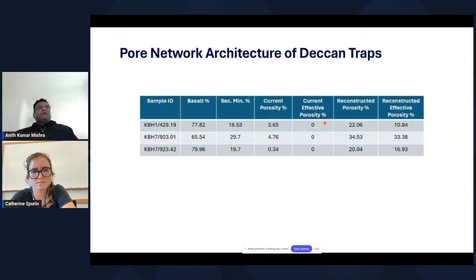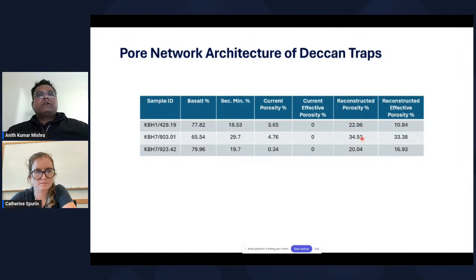So this is a table showing the basalt, the secondary mineral percentage, the current porosity, and the current effective porosity for the different samples taken from the Deccan traps. And the last two columns indicate the reconstructed porosity and the reconstructed effective porosity that have been eaten up by the presence of the secondary minerals. So this is basically the storage opportunity, or the storage potential, that has been lost for the Deccan trap